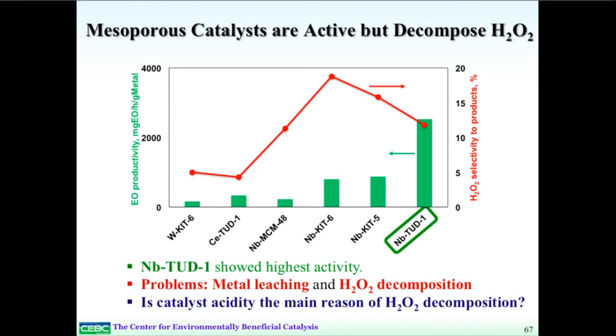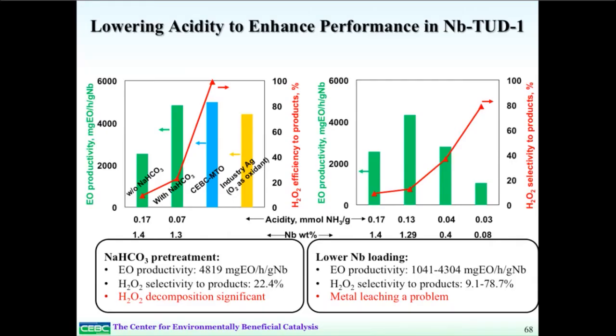This niobium TUD1 catalyst seems to work the best. There's also a problem with metal leaching, with the metal that's doped inside the catalyst, inside the pore, leaching out into the system. One hypothesis that we have is that it's the catalyst acidity which is causing this. So we've done a number of studies for this. One is actually experimental. To decrease the acidity, one is to pre-treat with sodium bicarbonate. This actually caused the productivity to go way up, to be comparable with the other CEBC homogeneous process and the industrial silver process.